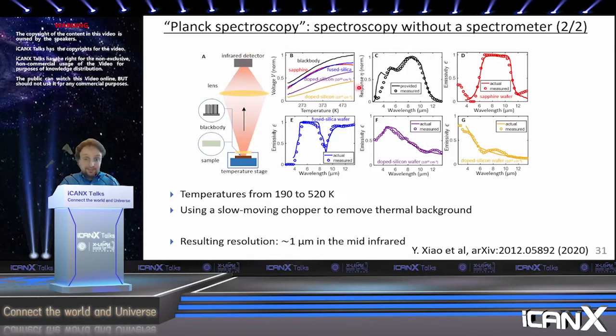So that's already kind of a cool result. But then we take this responsivity together with this experimental data, and we can measure the emissivity of a bunch of reference samples just to see how it works. So here we have a sapphire wafer, a fused silica wafer, a wafer of silicon doped to 10^20 cm^-3 using ion implantation and annealing. And here it's also a doped silicon wafer, but doped to 10^21 cm^-3.